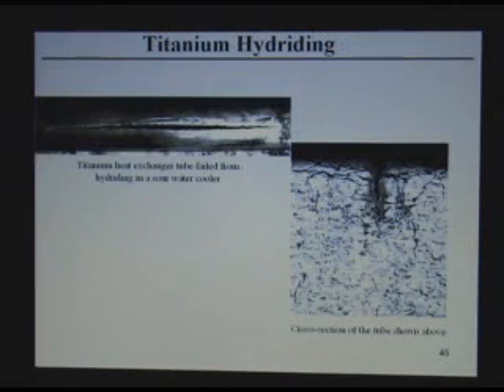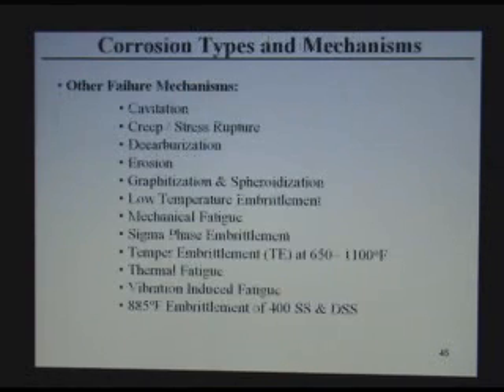Titanium hydriding: hydrogen goes into the metal and makes it brittle, and you end up with a crack all the way in a tube, and this is how it looks in the microstructure. There are other mechanisms of damage causing failure, like cavitation, which we see in pumps and control valves. If you have vacuum, what happens?